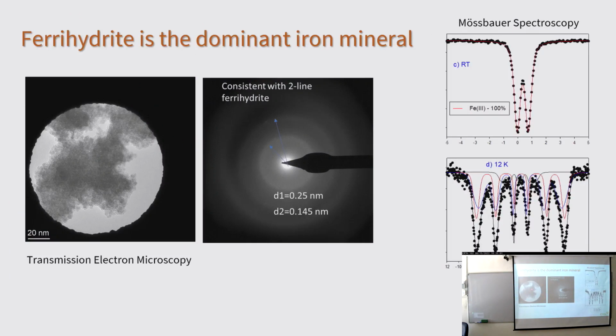And then we collected diffraction rings using the TEM, and the d-spacings here were actually consistent with two-line ferrihydrite. We were also able to collect some Mossbauer data of the colloids, and fitting of the data showed that we have the presence mostly of amorphous iron minerals, likely ferrihydrite, with different coatings of organic matter and silicon. So the Mossbauer and the TEM data complemented one another very nicely.